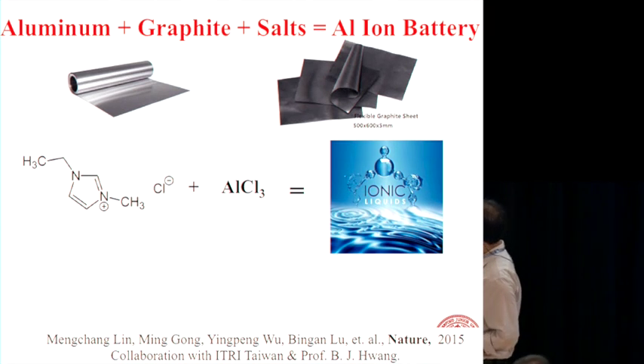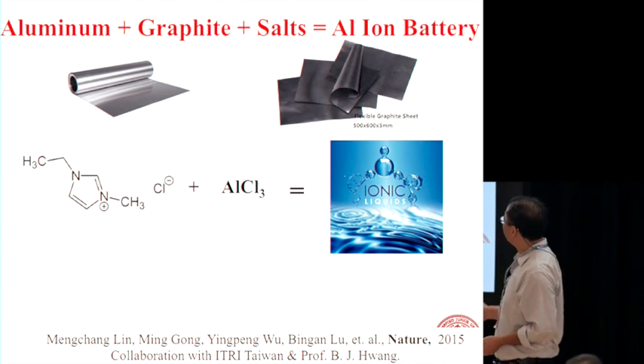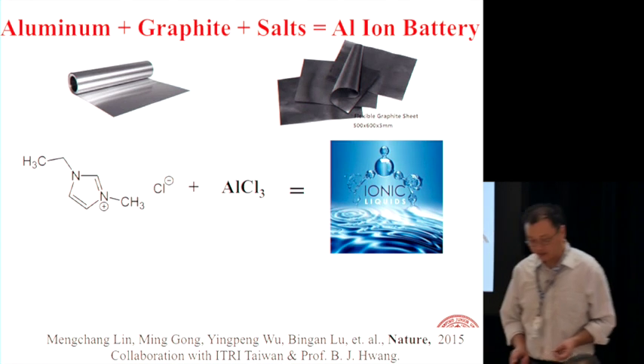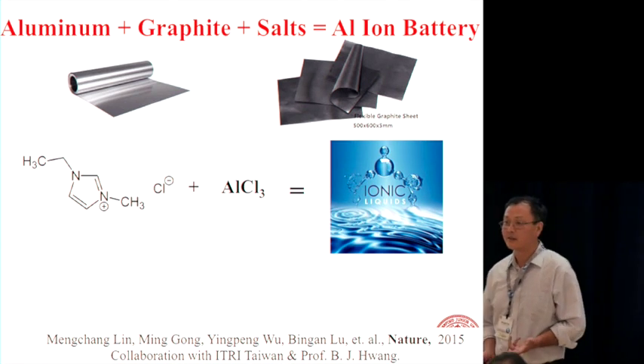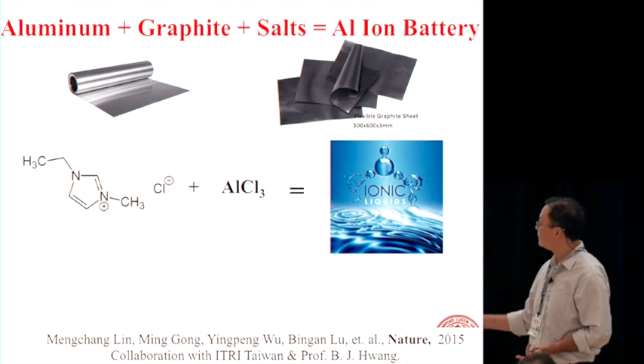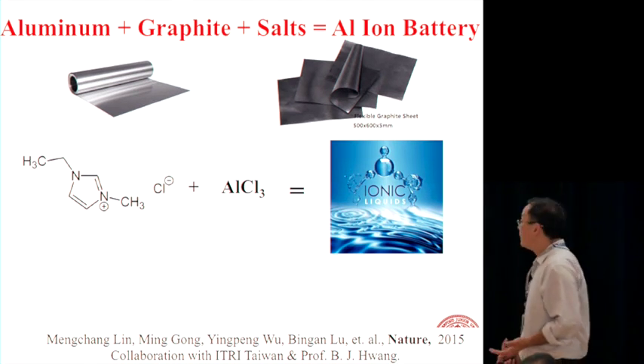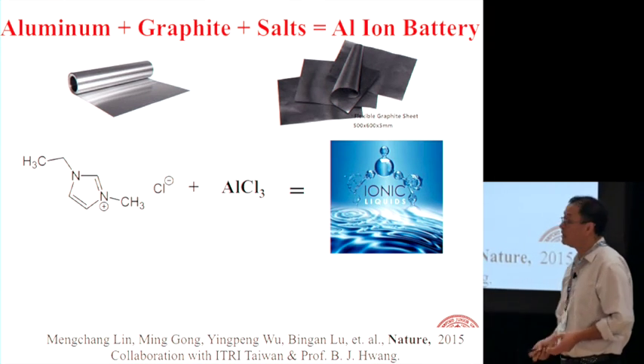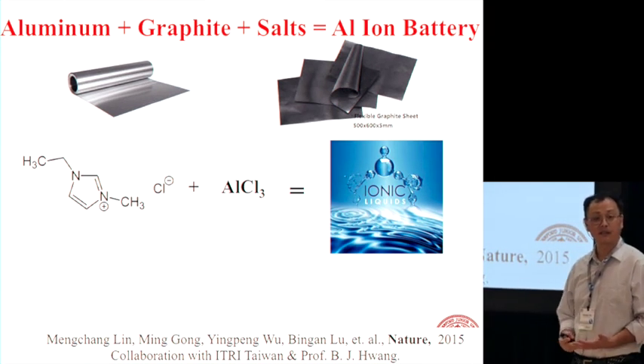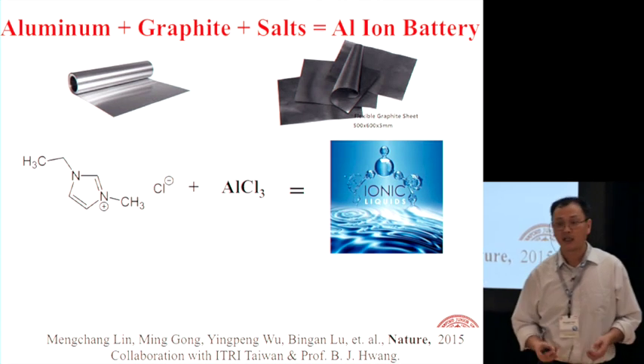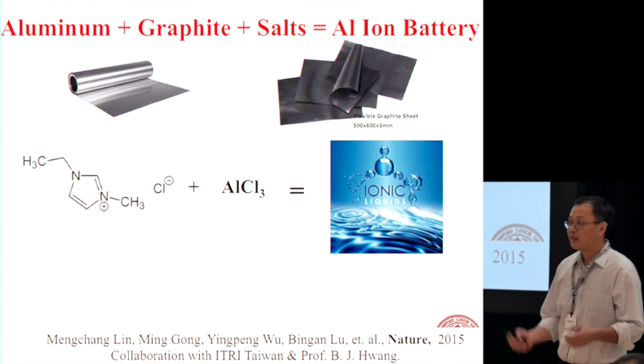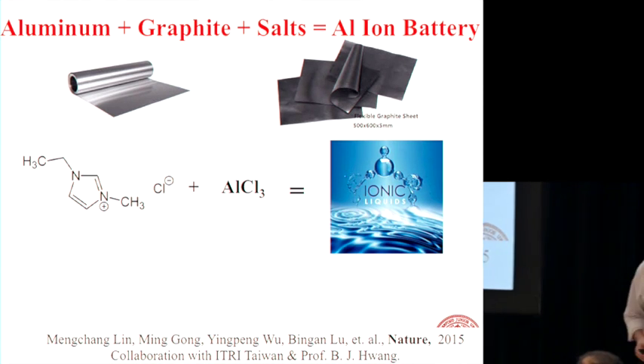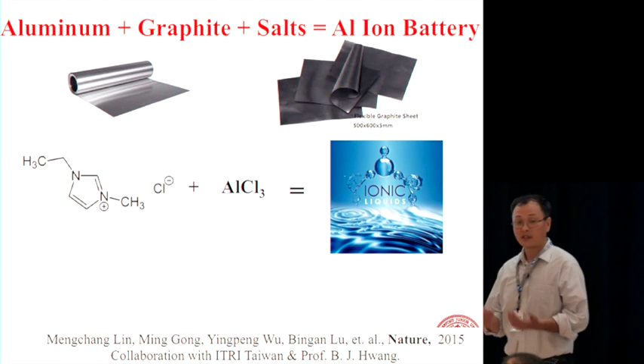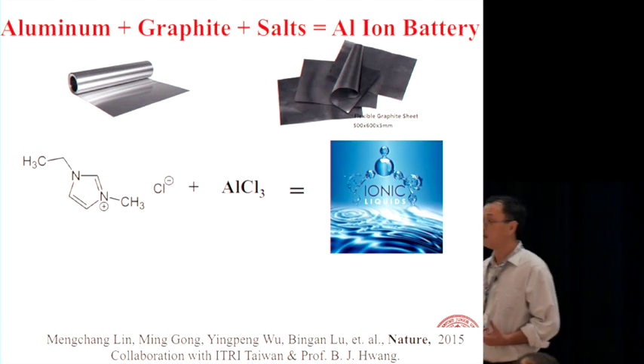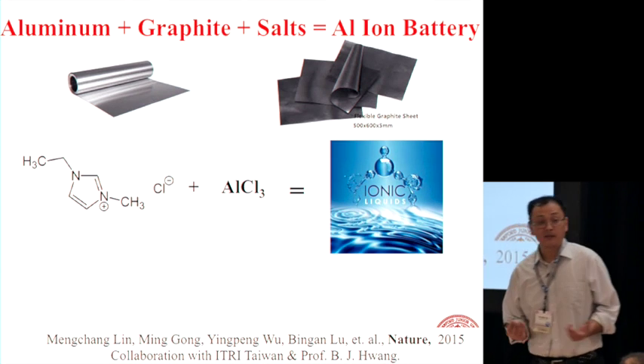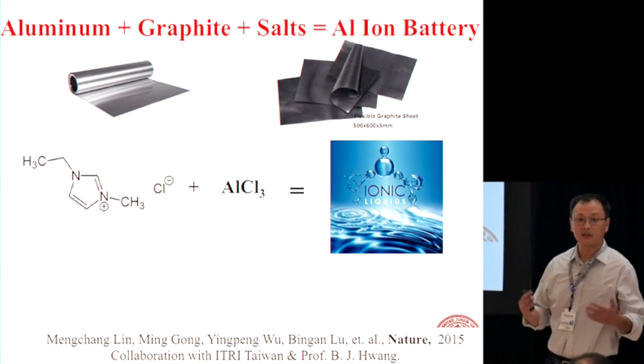And then these two are the two electrodes, but this electrolyte is actually a little special. It's made of salt. Okay, there is organic salt plus aluminum chloride. Remarkably, you mix them together, it makes a liquid. Okay, because there's so much entropic gain by mixing intimately, it actually lowers the melting point a lot. So it becomes a liquid at room temperature by mixing solids. Okay, it's fairly remarkable. But we didn't do this part. This is known for 30 years or 40 years.